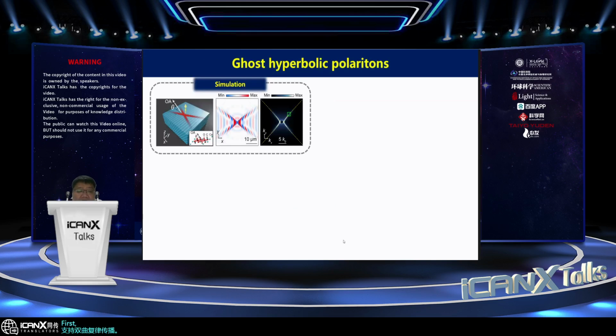Firstly, we built our theory. We consider a case where the angle between the OA and the calcite surface is 23 degrees. When we use a dipole to launch a polariton here, we can find a very similar in-plane anisotropic propagation. When we do the Fourier transform of the field distribution, we can get a polariton momentum distribution in k-space. It indicates a hyperbolic dispersion.